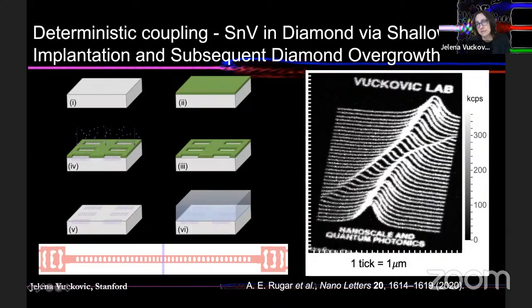And with this technique, we actually can introduce color centers at any position in the diamond structure where we like. I mean, even in the shape of my group's logo, which is not useful for science, but it just shows that we have control over this. And then subsequently, we can align optical structures to whatever positions of color centers we have. So that's one technique that could be used to address spatial inhomogeneities.